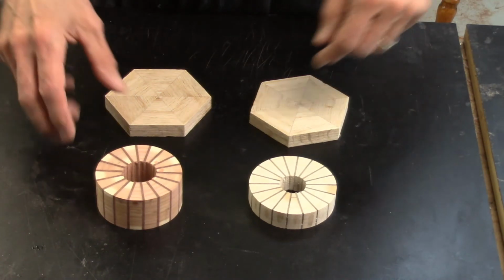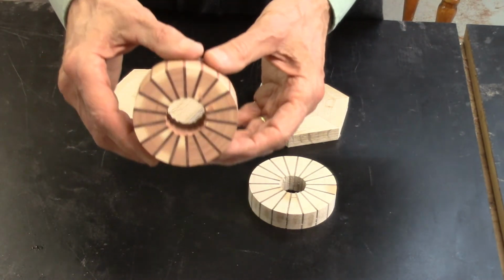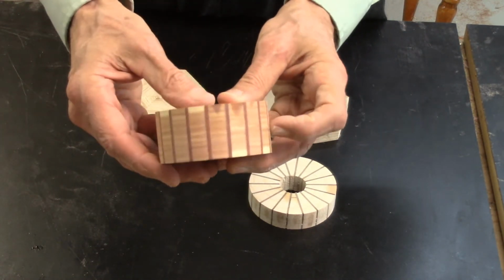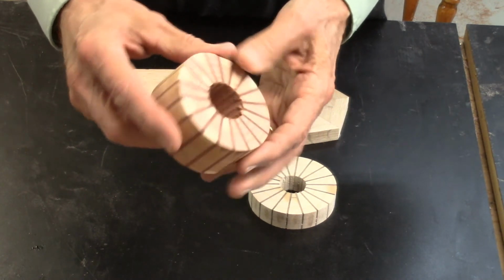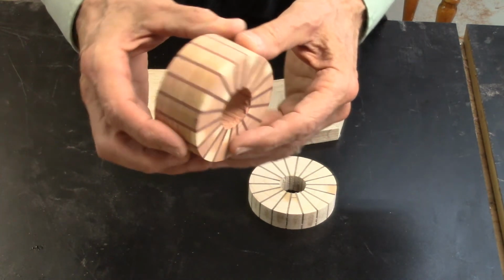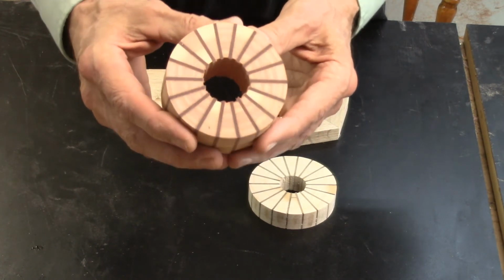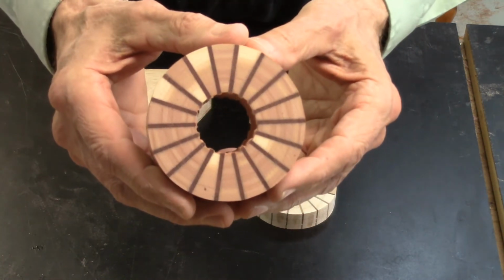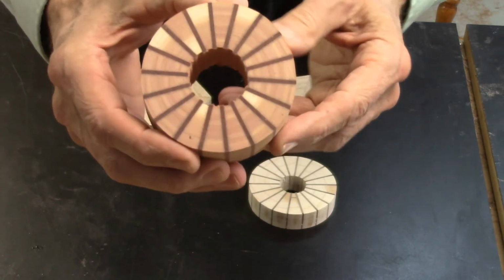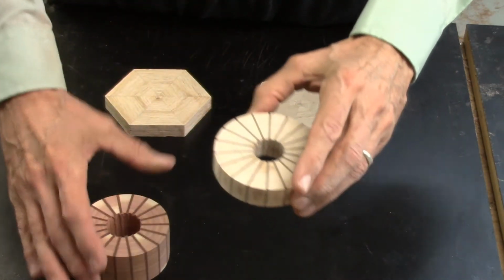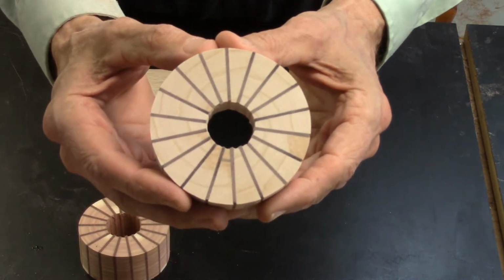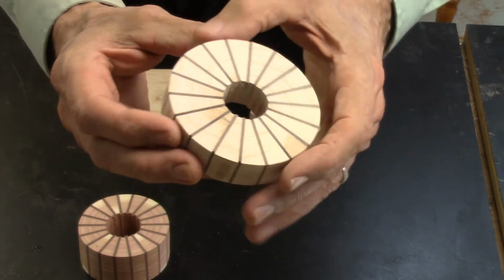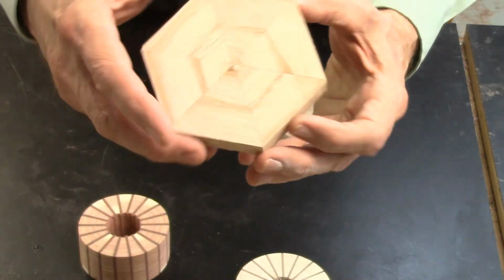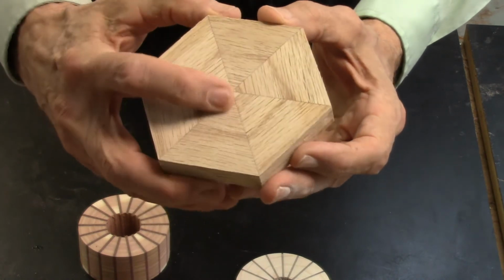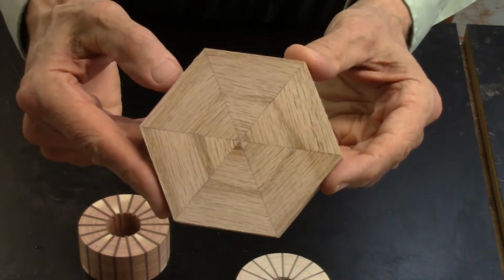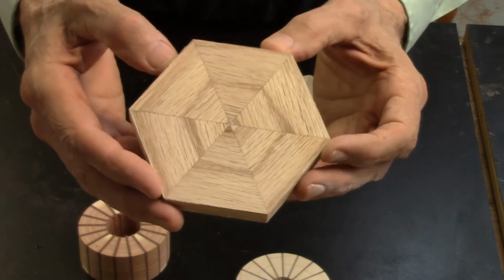After removing the rubber bands, sanding these discs on my edge sander, cleaning up the edges on a wire wheel, and then sanding them some more, this is our resulting segmented ring. Got nice tight joints, and it should hold up pretty well. Here's the second one, and then there's two of these going to a center point, perfect center on these. All glued with a thicker epoxy resin.